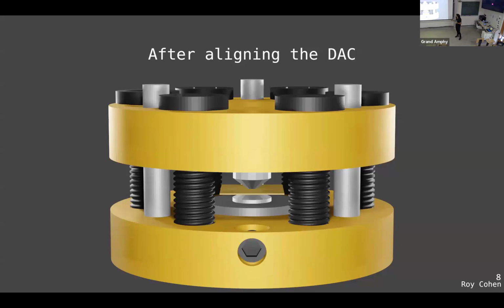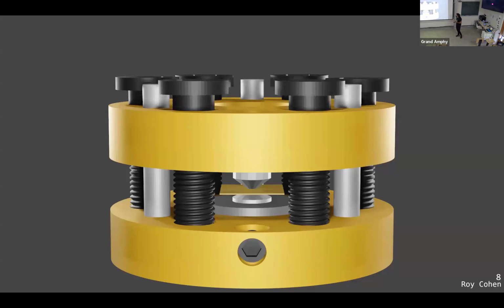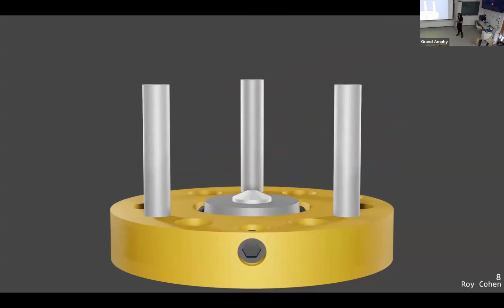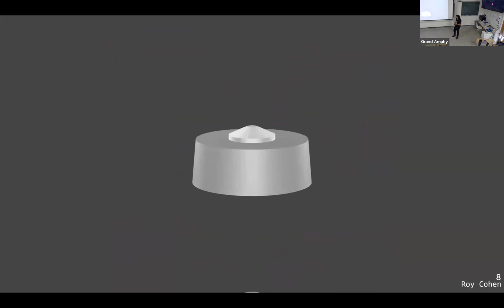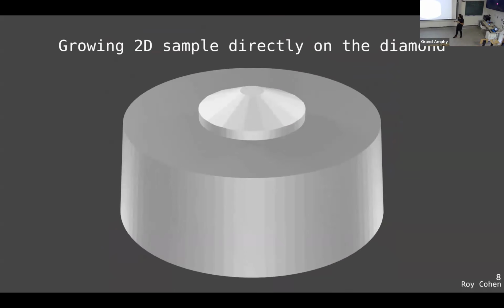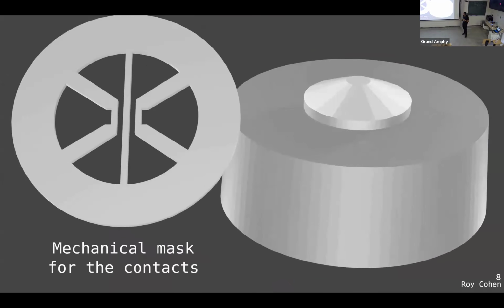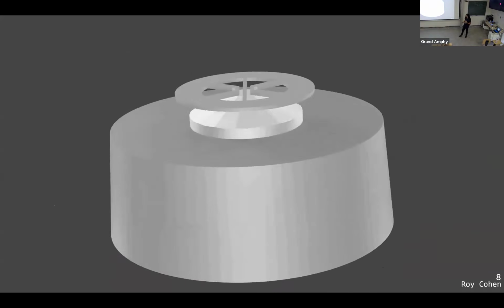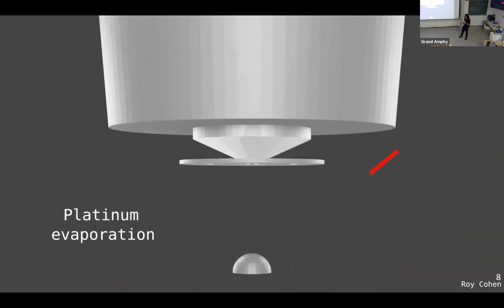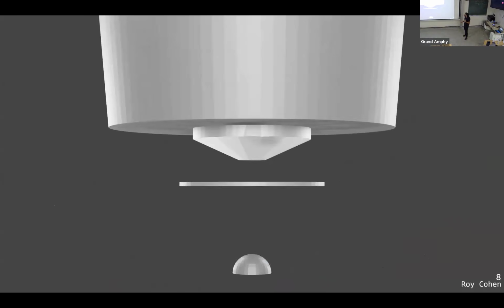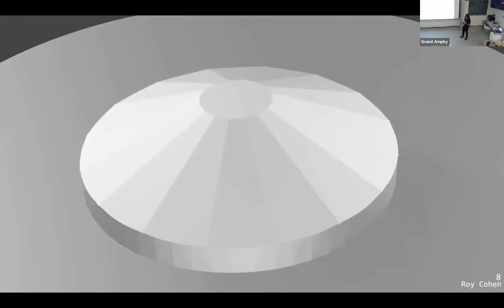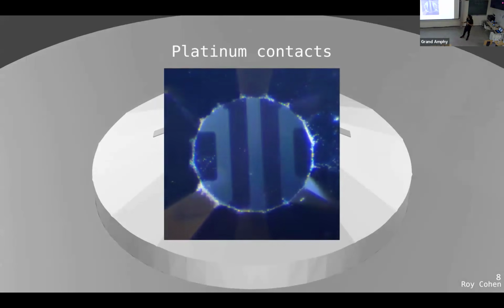So we have our diamond anvil cell. After aligning my 2 diamonds, I open the diamond anvil cell once again, take the bottom diamond out, and grow my 2D thin films directly on top of the diamond. So my diamond is my substrate. By using a mechanical mask, first I evaporate platinum contacts directly on top of the diamond, from the culet, the flat area, to the bevel. Here we have a microscopic image of our platinum contacts directly on top of the diamond.